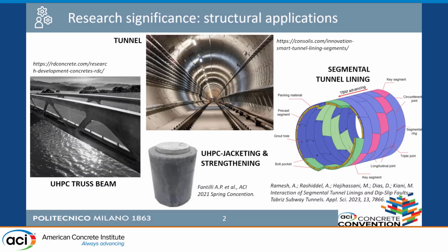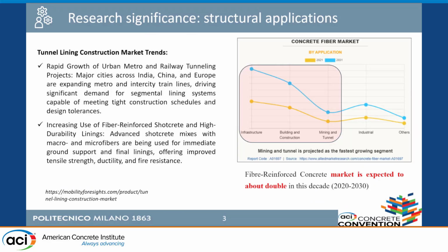So it's important to say that the tensile behavior, also under direct tension, is becoming more and more important. We cannot just speak about bending, but we have to move to tension to understand how this happens. Especially where we have jacketing, and so the confinement of the concrete inside, we also have members that are subjected to direct tension. The market of fiber-reinforced concrete is also increasing thanks to the pushing ahead of tunneling and infrastructures. So this is the reason why I mentioned this application before. In these cases, the problem is not only compression, obviously, but also tension, and especially what happens in the residual condition, to understand if some rehabilitation or strengthening has to be performed in the structure.